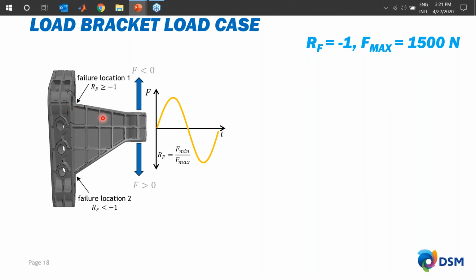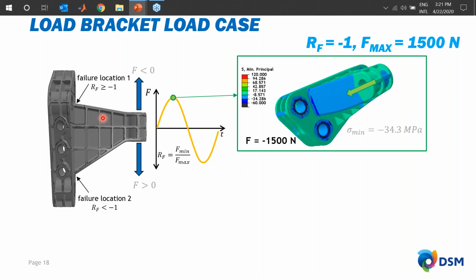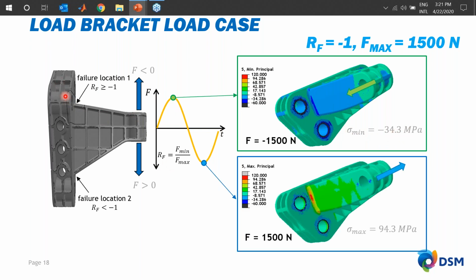Then the next thing you can do, besides looking at the failure locations, is looking at the stress levels. If you do so at, let's say, a load of 1500 newtons, if you push with 1500 newtons, you end up with a compressive load here on the top of -34.3 MPa. But if you then look at the stress levels in the same region, when you pull with 1500 newtons, then you can see that the load is much higher. So it's 94.3, partly due to this anisotropy and partly due to the boundary conditions because of washers that are applied while applying the bolts.